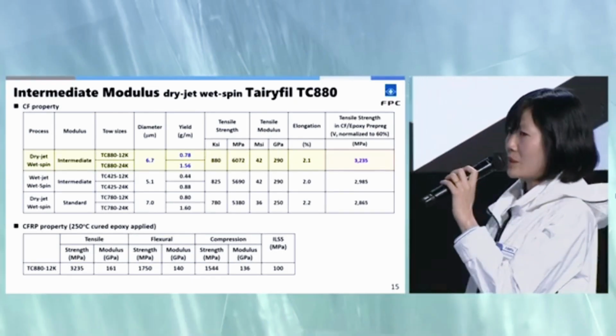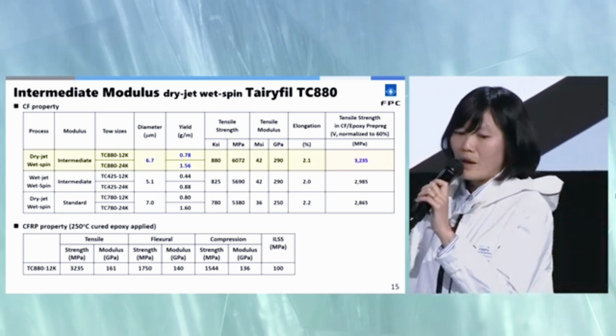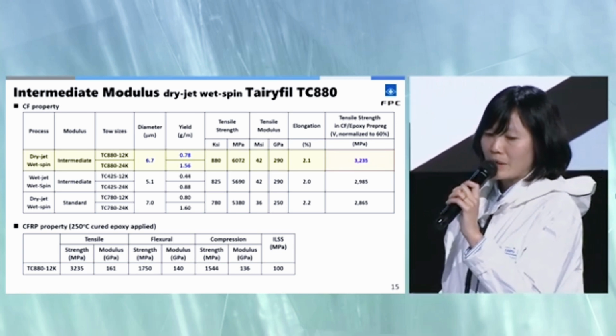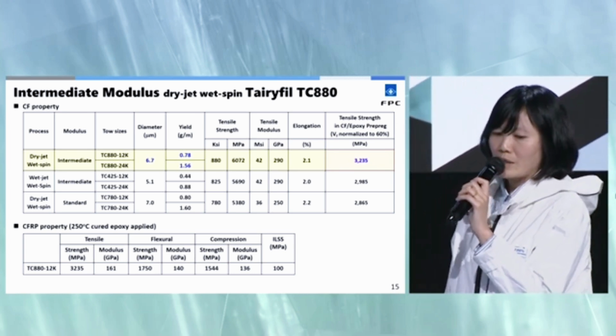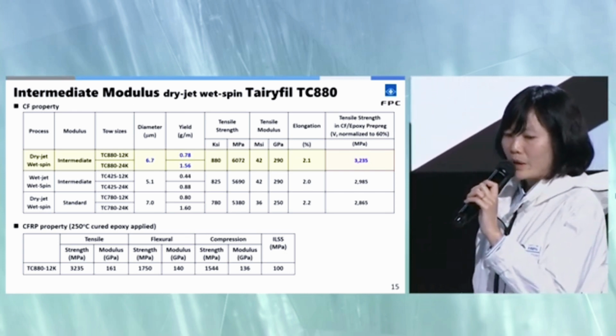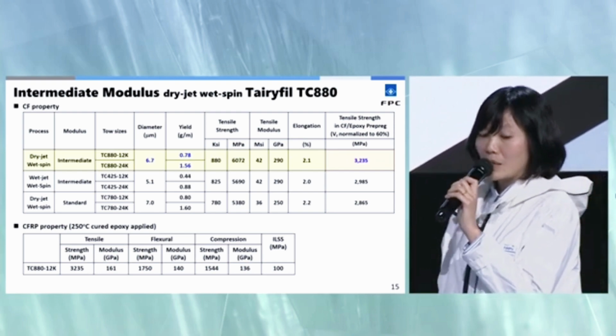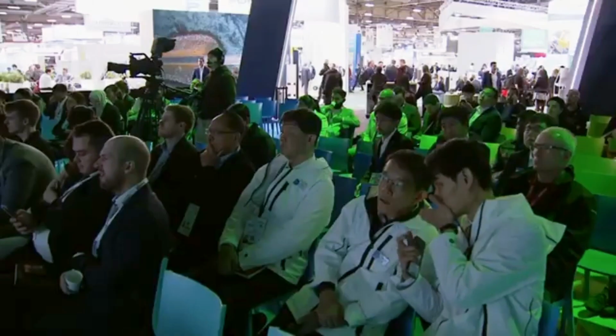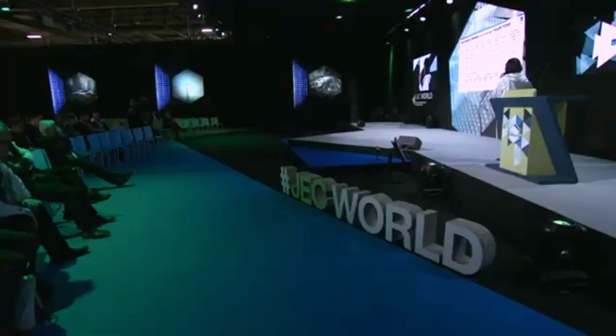Here I summarized all the carbon fiber properties of our dry jet intermediate modulus fiber TC880, and you can see its diameter and yield are similar to those of our TC780, our standard modulus fiber, and different from our wet jet intermediate modulus fiber, which is larger in diameter and yield. You can also see the tensile strength for TC880 is higher than TC425, our wet jet intermediate modulus fiber, and also the epoxy-based composite. The table here summarizes the composite properties for your reference: the tensile, flexural, compression, and ILSS.